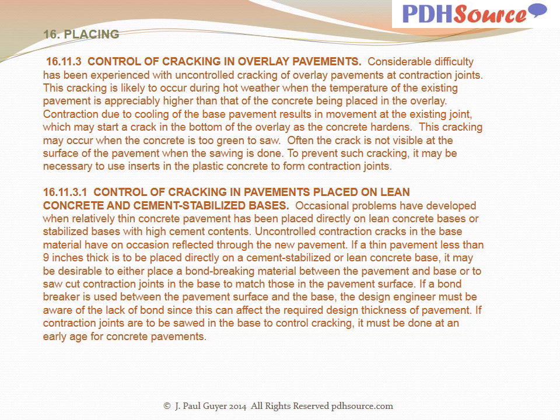This cracking may occur when the concrete is too green to saw. Often the crack is not visible at the surface of the pavement when the sawing is done. To prevent such cracking, it may be necessary to use inserts in the plastic concrete to form contraction joints. Occasional problems have developed when relatively thin concrete pavement has been placed directly on lean concrete bases or stabilized bases with high cement contents. Uncontrolled contraction cracks in the base material have on occasion reflected through the new pavement.